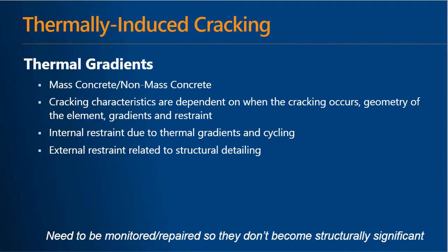Again, I'm going to touch on thermally induced cracking. Karla mentioned this and went over some of the features, but I wanted to reintroduce it because, like Karla said, there can be many mechanisms contributing to the cracking, and we want to remember that they can be additive, like drying shrinkage and thermal cracking. But in order to have thermally induced cracking, again, there needs to be some type of restraint. Again, whether that's internal restraint due to thermal gradients and temperature cycling within an element, or external restraint related to something like structural detailing.